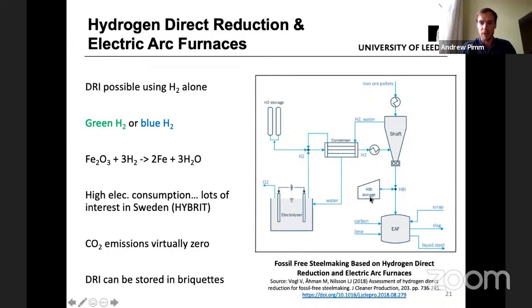But anyway, there's an overview of the approach in the figure on the right here. You can see you have an electrolyzer splitting water into hydrogen and oxygen, so you have some waste oxygen there. An important question longer term would be, what might you do with that oxygen? To use the hydrogen, you need to raise the temperature to about 800 degrees C. You can do that using some waste heat from the top gas. You then pass the hydrogen into the shaft furnace. It enters at the bottom, with counterflow as the iron ore flows down.